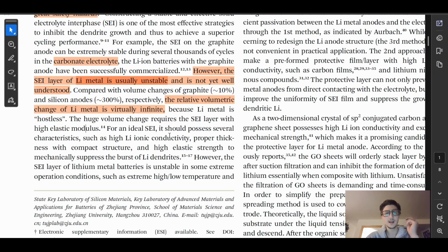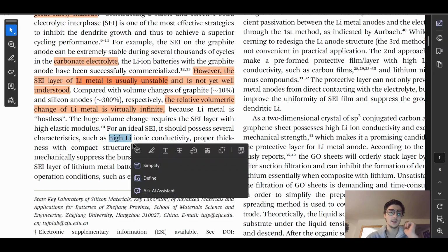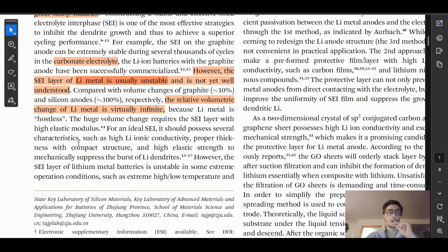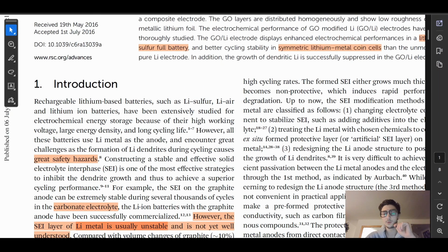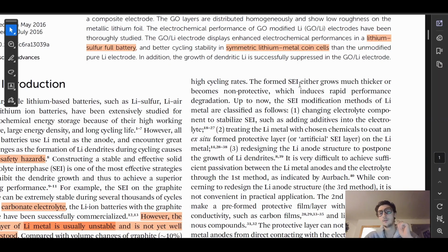Interesting. For an ideal SEI, solid electrolyte interface, it should possess several characteristics such as high lithium ionic conductivity, proper thickness with compact structure, and high elastic strength to mechanically suppress the burst of lithium dendrites. This is a cool sentence here. For an ideal SEI. And they give you some citations there as well. However, the SEI layer of lithium metal batteries is unstable in some extreme operation conditions, such as extreme high/low temperature and, going over to the other side here, high cycling rates. The formed SEI either grows much thicker or becomes non-protective, which induces rapid performance degradation.